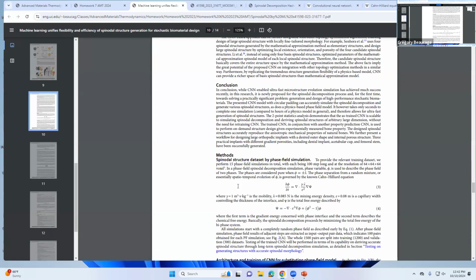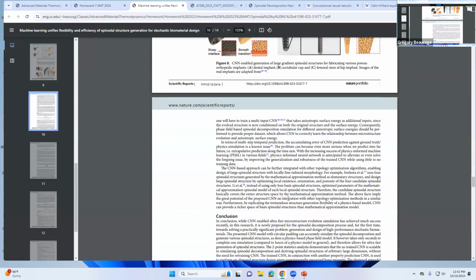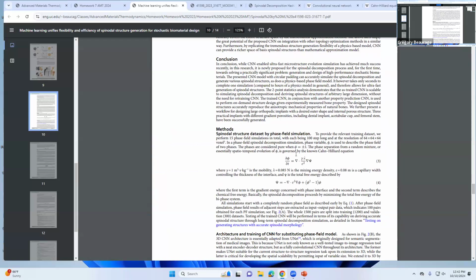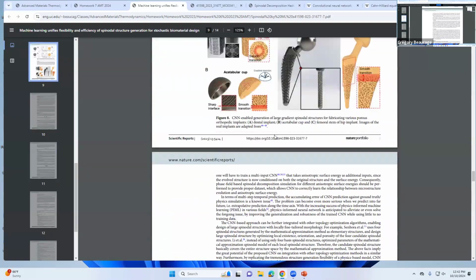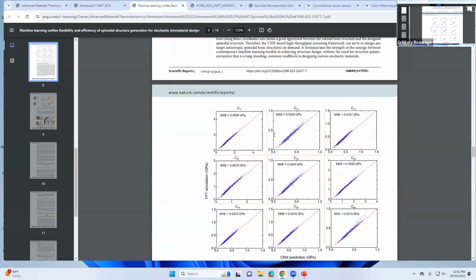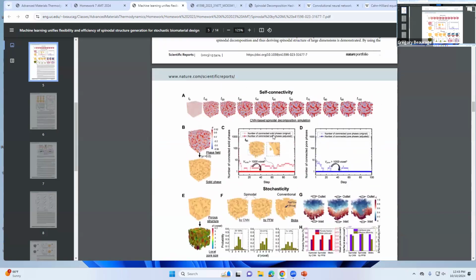In the case where you're actually trying to do something, probably not, but basically people do it anyways, especially computer simulation people. So he takes a finite element simulation, which is going to be like a grid with points, and then concentrations between the points. He's going to use this equation, the Cahn-Hilliard equation, to create a time sequence of events of the growth of this thing. So he's got pictures of that in here, of the growth of the spinodal, and he gets something that's pretty close to what it's like.